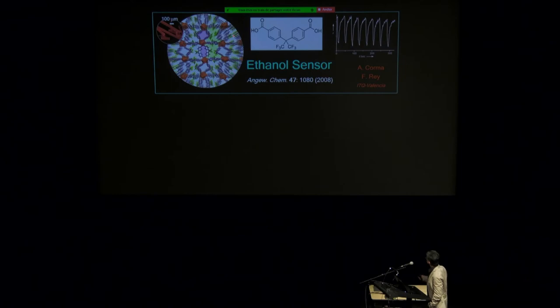So what we have here is one example where we have 8 and 9 coordinated europium oxygen polyhedra. And you can see there are two types of channels here. I don't want to go into details. That's the molecule which links the clusters. And with this structure, we could actually make an ethanol sensor.